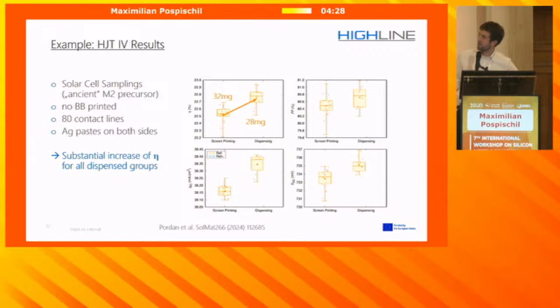And yeah, let's show you some examples of IV results. These are, I call it, ancient M2 precursors. And they have no bus bars. And we compared screen printing with dispensing with the same paste, still silver, unfortunately, but it's silver. And what you see, we applied dispensing, and even though printing fewer milligrams, we had an increase in the JSC due to the small line width, VOC then the same thing, and then better silver usage. We increase the fill factor, and then we have an increase in efficiency here.